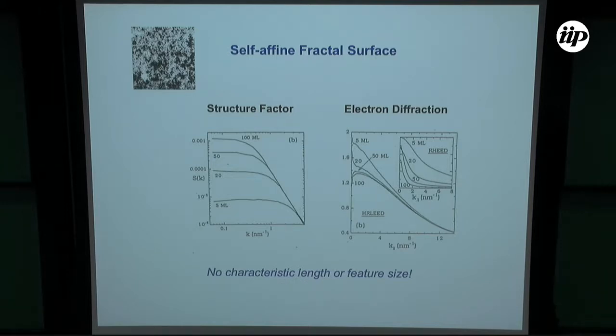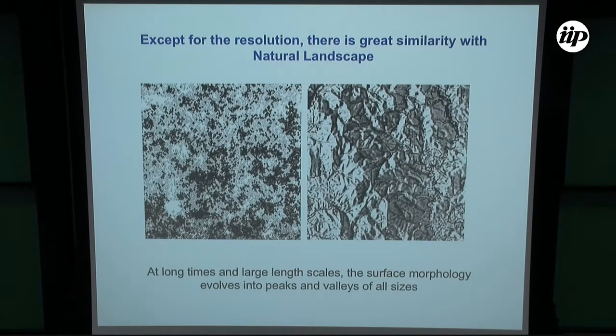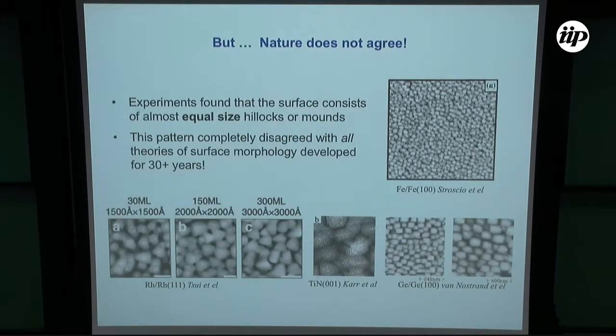So what happens when you do experiments in MBE growth? Well, nothing like that is found. So I already talked about that. Experiments don't find anything like this. Nature basically does not agree with what we thought made a lot of sense, right? There were many simulations, a lot of theoretical work done on this problem, and all of them thought that the important thing was to measure the exponents alpha, beta, and z, and try to come up with better simulations or better theoretical ways of calculating those exponents.